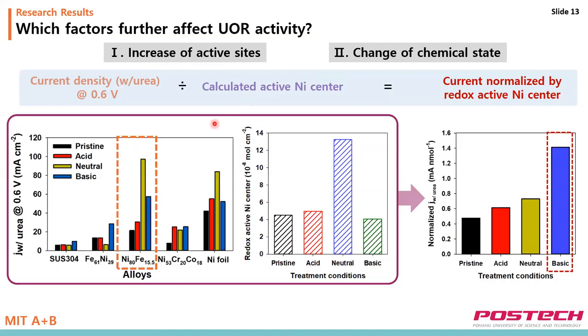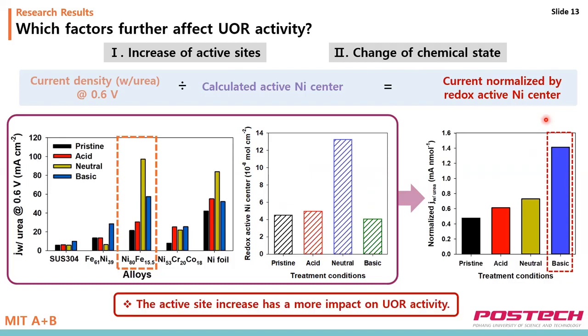Until now, the factors affecting the increased UOR activity are largely divided into two parts. First, increase of the active site, and second, creation of hydroxide and oxyhydroxide foam on the surface. Therefore, in order to find out which factor further affects the UOR activity, the current density was divided by active nickel center. The normalized current shows that electrodes treated under basic conditions show the highest activity. This means that the intrinsic activity was the most increased when treated under basic condition. Here, in sum of the results, the active site increase has more impact on performance improvement.